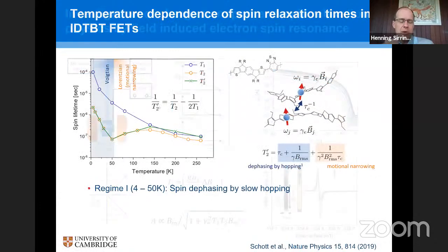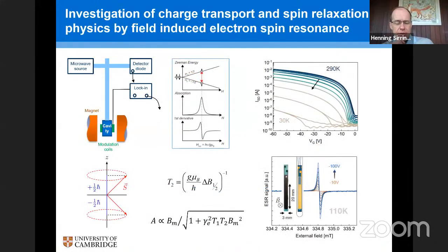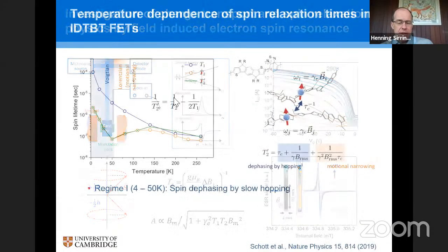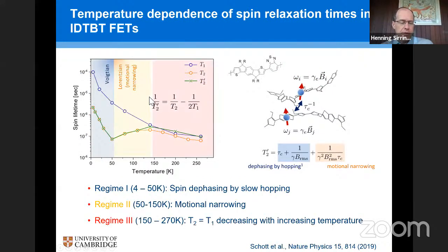And so from the line shape, the line widths, and how the line shape saturates with microwave power in an ESR experiment, you can extract the spin relaxation times T1 and T2 in these systems. And here you can see a summary plot of the spin lifetimes. T1 is in blue here, the top line, and then in orange is T2. And you can see this characteristic behavior. T1, as you go from low temperature to high temperature, decreases monotonically from quite long values of hundreds of microseconds at low temperatures to still moderate values at room temperature.